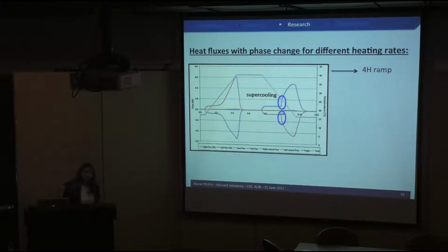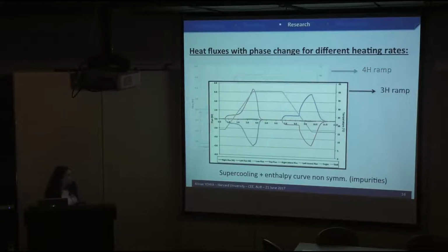Supercooling can have side effects because if it is not included in the design, it can shift the fusion times, and we can have some errors in the design. If no supercooling occurred, we should have seen the curve with more smoothness. So we tried changing the ramp to 3 hours to see how this affects the supercooling. We can see that it does, because supercooling relies on the kinetics. The rate of cooling of the material affects the degree of supercooling. Here we still have supercooling, but the degree changes.